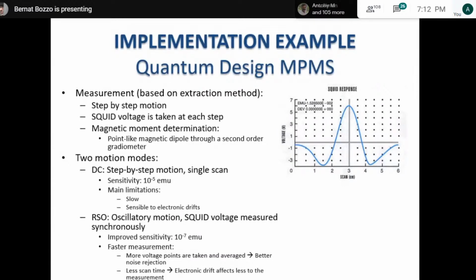The sample is placed at the end of the sample rod. However, this method is quite slow and very sensitive to drift, since a measurement like this takes normally about half a minute. If you have some electronic drift, the voltage at the beginning and the voltage at the end are no longer the same.